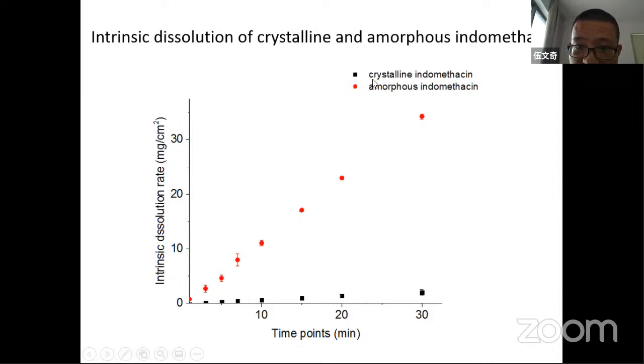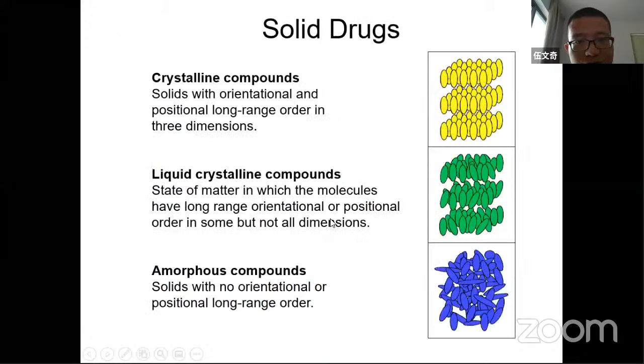Black dots represent crystalline indomethacin. This is time, at 10 minutes, 20 minutes, 30 minutes, and this is the intrinsic dissolution rate. We can see black dots and red dots. The red dots are from amorphous indomethacin. We can see very obviously the dissolution rate of amorphous indomethacin is much faster than crystalline indomethacin. This is an example with indomethacin.